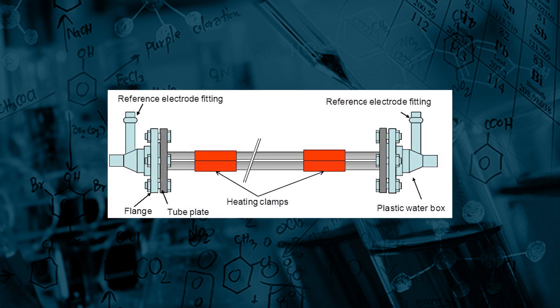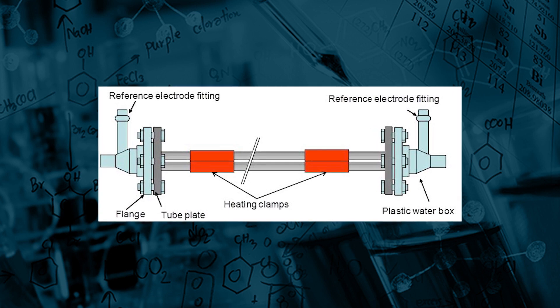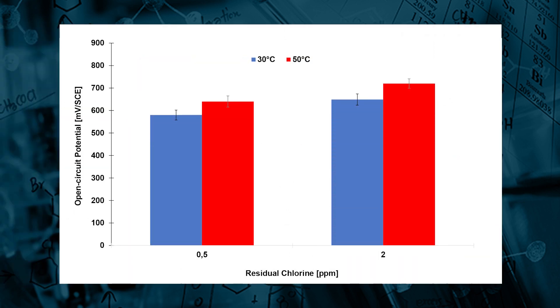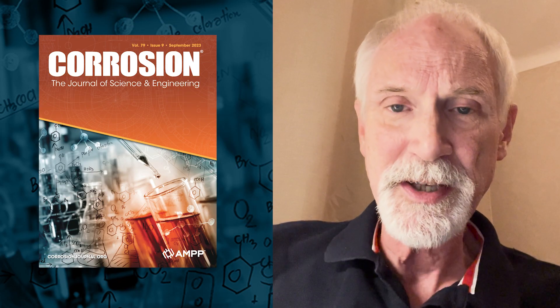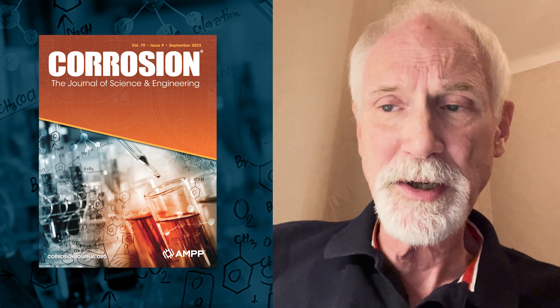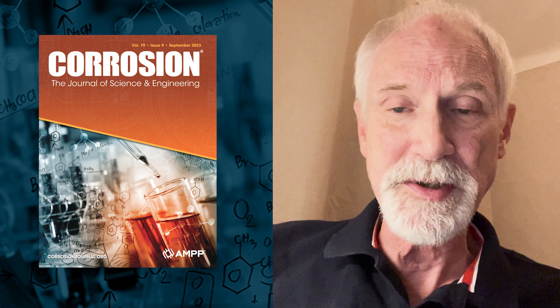Experiments included conventional electrochemical methods to evaluate the effect of biofilms and free chlorine on the cathodic reactions and the open circuit potential. These electrochemical studies were correlated with corrosion under simulated user conditions, either as an internal tube under heat flux or in simulated crevice environments.